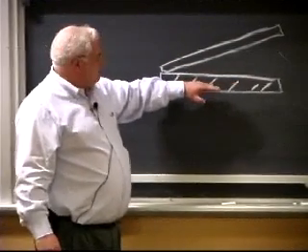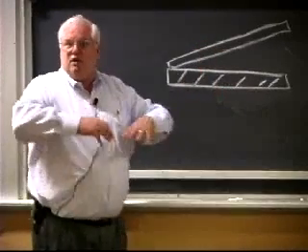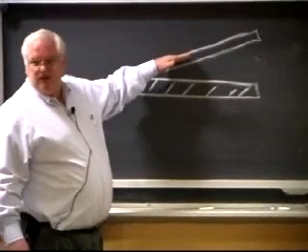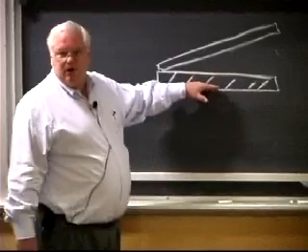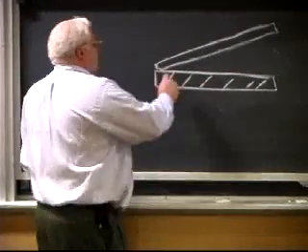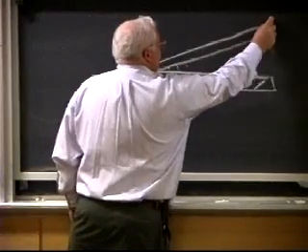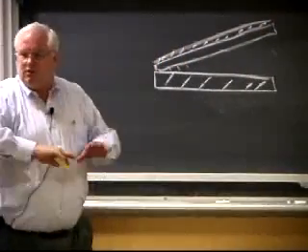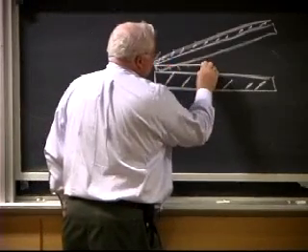Let's say this is a steel plate, and I want to put stainless steel or a nickel-based alloy or something else on top of it, and use that as part of a chemical pressure vessel where I have the expensive material on the inside where I need it, and I have the steel on the outside for the strength. It turns out there used to be two places, I think there's only one left in the world, where you would line the top of this plate with an explosive, which comes as plastics and stuff. You just put this explosive on here and ignite it, and the plate would be forced against the surface.